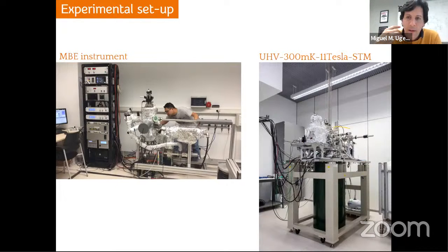And the main tool for us is this system. It's a UHV STM that works at a base temperature of 300 millikelvin, and we are allowed to apply a magnetic field of 11 Tesla. So once we get this sample into the prep chamber in this second system, we basically anneal at very low temperatures, around 200 Kelvin, and that's enough to remove the capping layer of selenium and expose the crystalline superconductor.